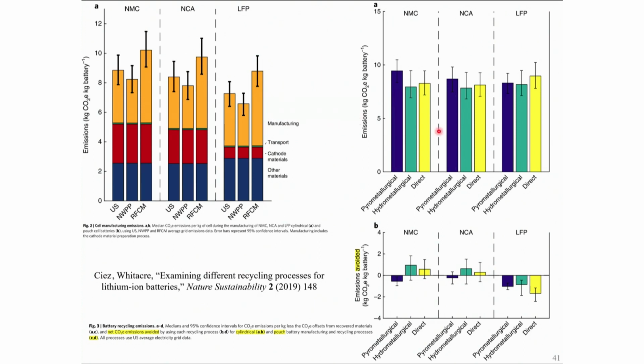Compared to the recycling approaches, where you have the pyrometallurgical recycling, which is similar, in some sense, to the mining of the original ores. You have the hydrometallurgical recycling, where you dissolve the battery waste into acids, and then try to extract the elements like nickel or lithium element by element, or so-called direct recycling, where you try to anneal the waste powder by adding in some lithium. So it turns out that in these recycling approaches, the amount of CO2 emitted is similar to manufacturing them anew. And in fact, for lithium iron phosphate, you would actually emit more CO2 than making new lithium iron phosphate.